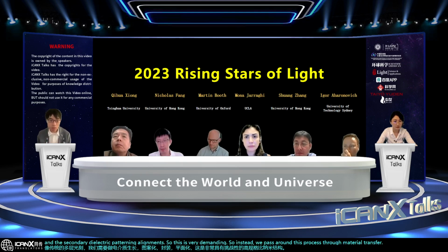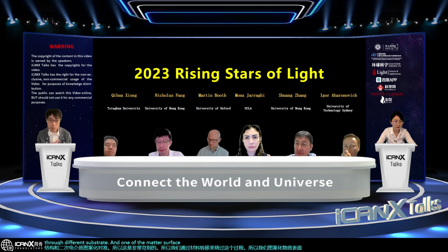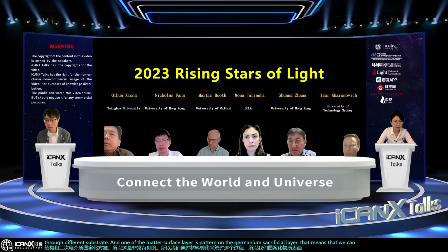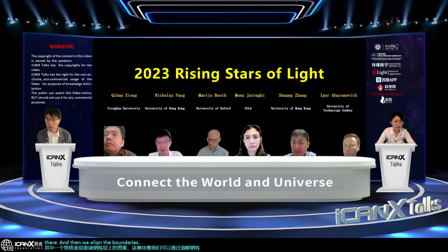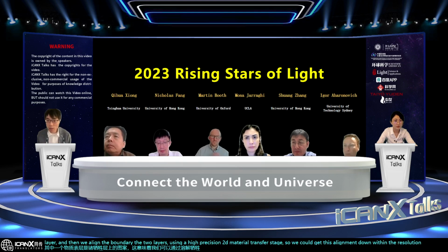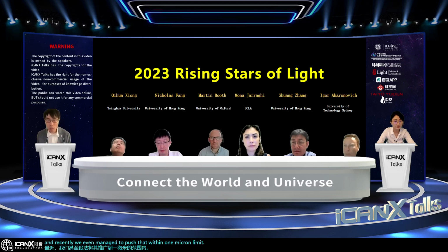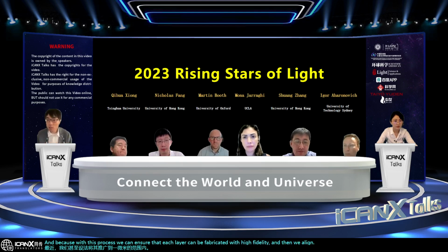We pattern the metasurface on different substrates. One of the metasurface layers is patterned on a germanium sacrificial layer. That means we can transfer that layer of pattern by dissolving the sacrificial layer. Then we align and bond the 2 layers using a high-precision 2D material transfer stage. We could get this alignment done with a resolution of 1 or 2 microns, and recently we even managed to push that within the 1 micron limit. With this process, we can ensure that each layer is fabricated with high fidelity, and then we align. So this is much easier to scale up to 3 layers.